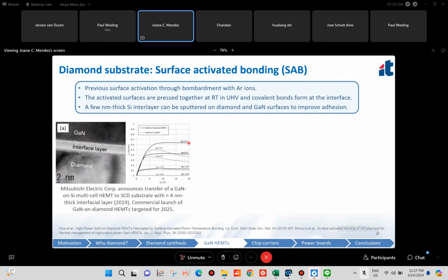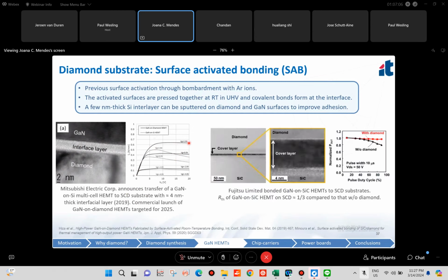GaN on diamond HEMT. And 1 year later, Fujitsu also reported having bonded a GaN on silicon carbide HEMT to single crystalline diamond substrates, thereby reducing the thermal resistance to 1/3 compared to that without diamond.